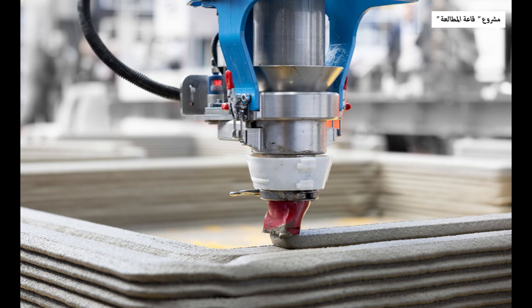If your temperature or cooling rate is off, you just don't get enough diffusion. And when diffusion fails, we end up with one of the biggest limitations of 3D printing, anisotropy. Correct. Anisotropy means the material strength is different depending on the direction. Think of wood grain. It's incredibly strong lengthwise, but splits easily across the grain. I see. In a failed print, the part is strong on the horizontal plane, where the material is continuous, but extremely weak vertically along those layer lines because the bonding was bad. Overcoming that is the holy grail of AM research.